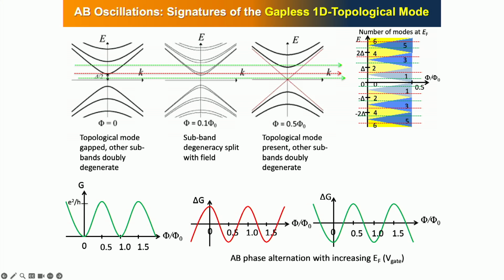So if you measure conductance, this is just delta G, but in this one you go from 2 to 1, so it goes from high conductance to low conductance. And this one goes from 2 to 3, so you should go from low conductance to high conductance. And so if you just measure delta G, you should alternate the phase of your oscillations. Okay? And that's the sign that you're sweeping through multiple subbands. And your overall conductance scale should also increase, which it does, but the image I showed you is a little bit artificially separated.